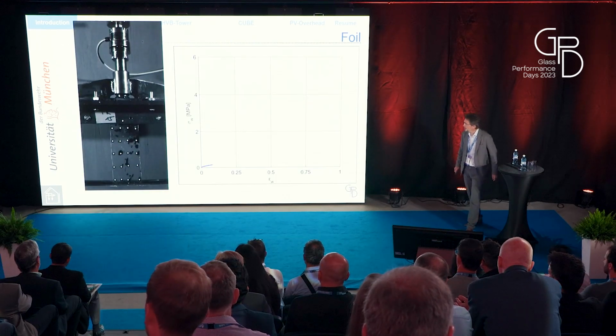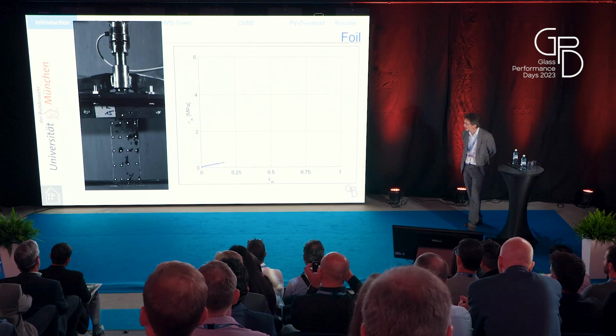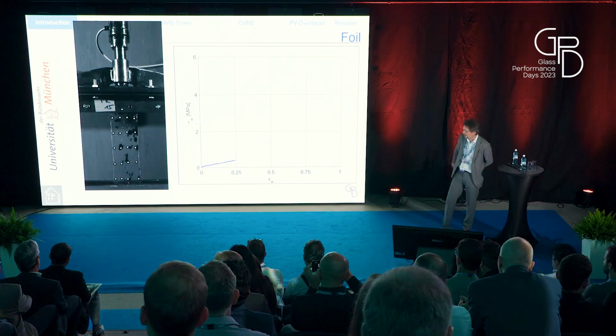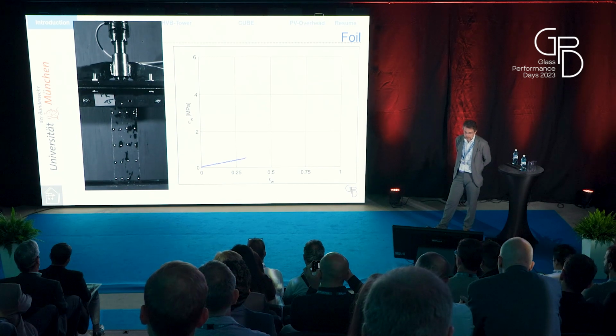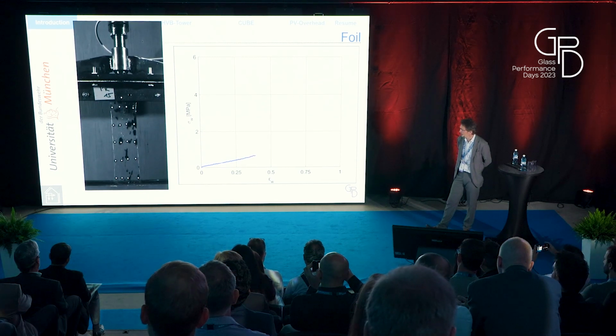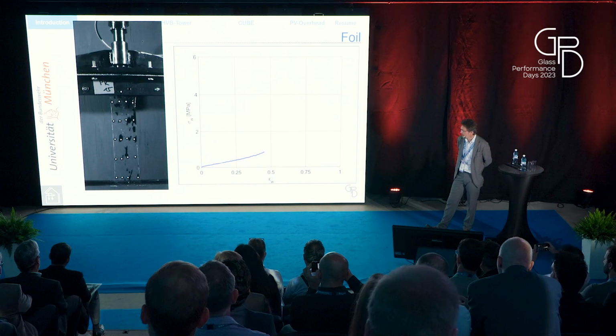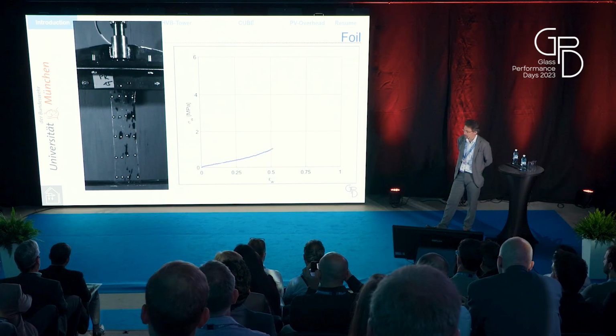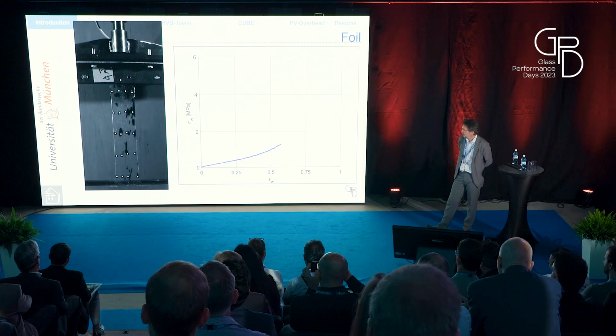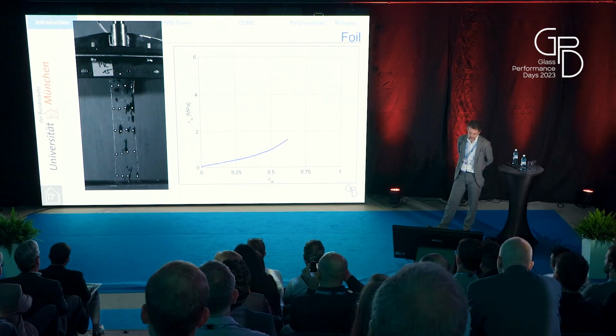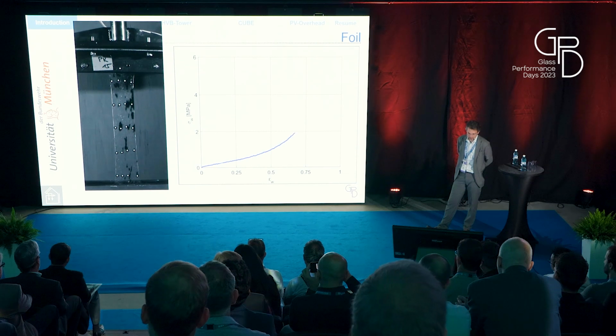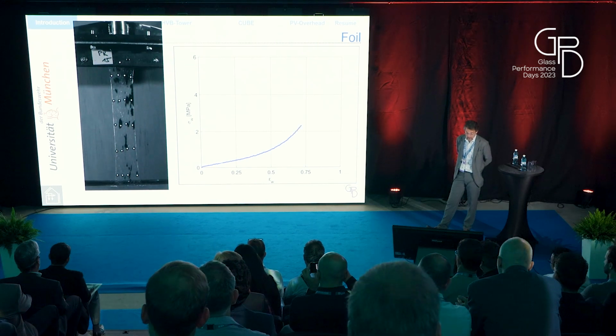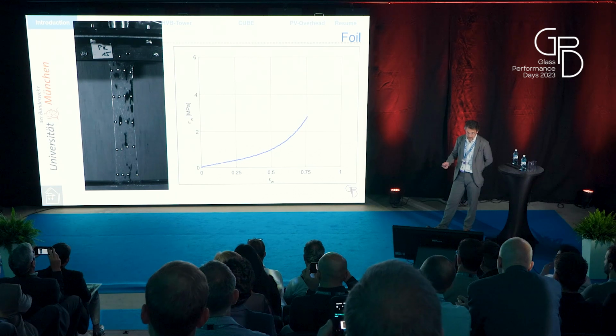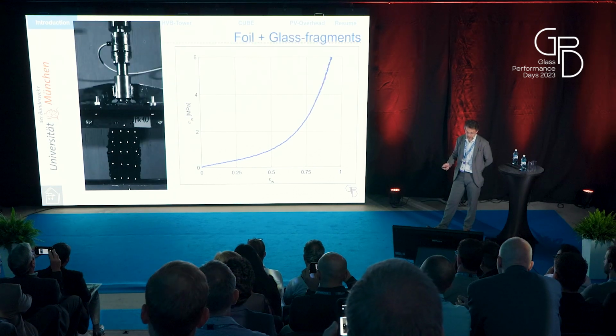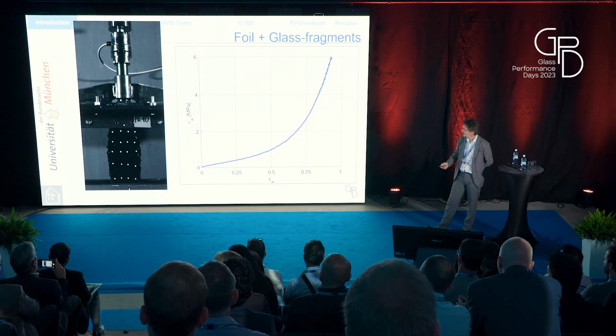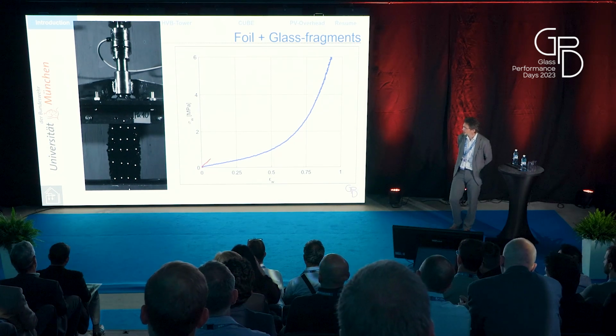Behavior of the foil itself, as you see here on the tension test, you see the stress over the strain curve, that is to say force over deflection more or less, and you see after a more or less linear beginning, it goes to the nonlinear phase. Yeah, it's a slow testing, sorry for this. But we can just go to the next slide and see what's happening if we have glass plus foil.